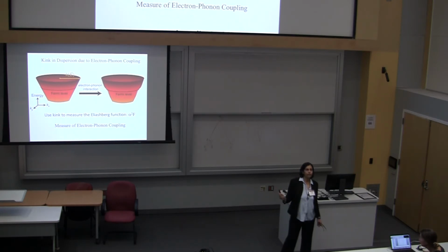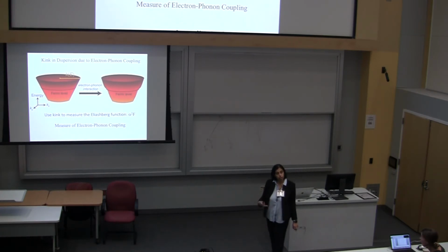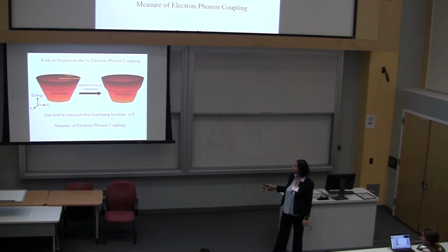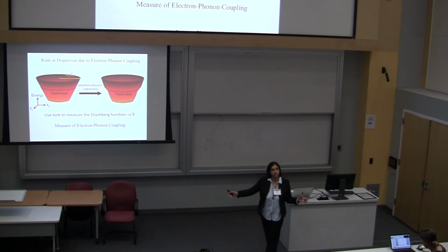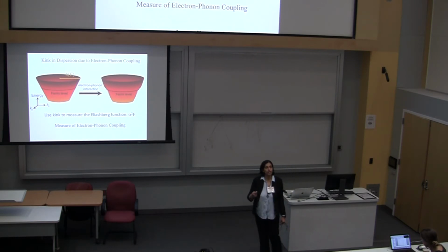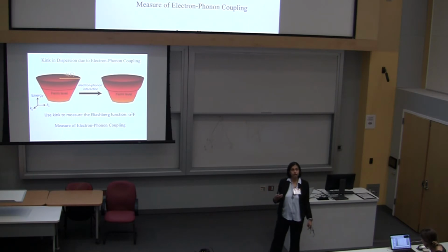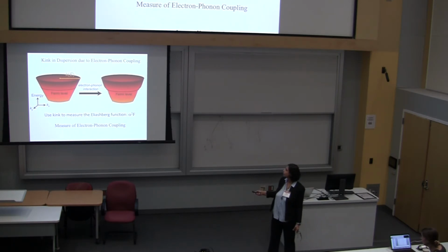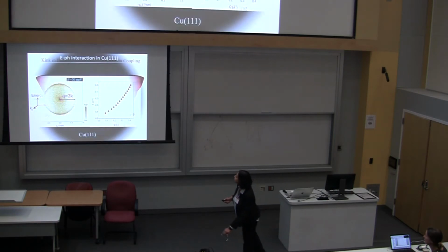So our goal when we started doing this was to actually measure this kink and to use it to get a measure of how strongly the electrons are coupled to the phonons. And that's actually given by something called the Eliashberg function, which is alpha squared times F. F is just the phonon density of states spectrum as a function of omega. And alpha is how strongly each phonon couples to the electrons. So this alpha squared F encodes all of that information. So we wanted to measure electron-phonon coupling using the STM.